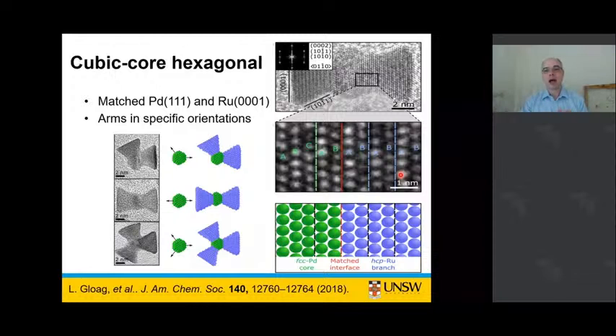So the second type of particle that we looked at, and this again was deliberate, was palladium, which has a very good lattice matching with ruthenium. So we thought in this case, if we use palladium seeds, we should have the good lattice matching and we should start to see this epitaxial growth and this orientation. And that's exactly what we did see.